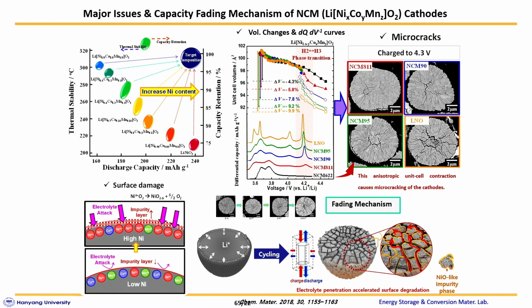As you know, these are the general intrinsic characteristics of the NCM cathode materials. As you can see here, increasing nickel content raises the discharge capacity, but the capacity retention and the thermal stability accordingly decrease. Based on this result, it is impossible to develop an ideal cathode by just changing the chemical composition. However, we need a cathode material at this point with high capacity, good cycle life, and safety. And before that, we should know the degradation mechanism of nickel-rich cathode materials.